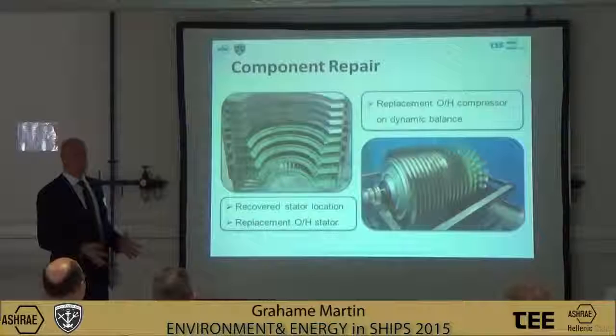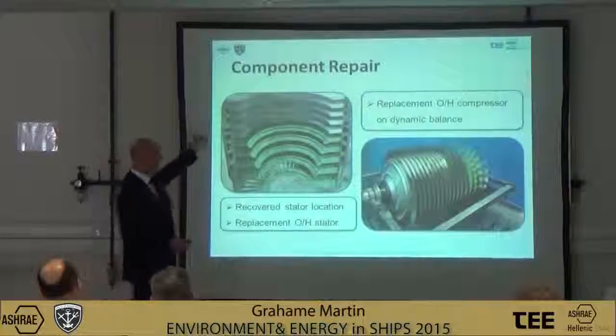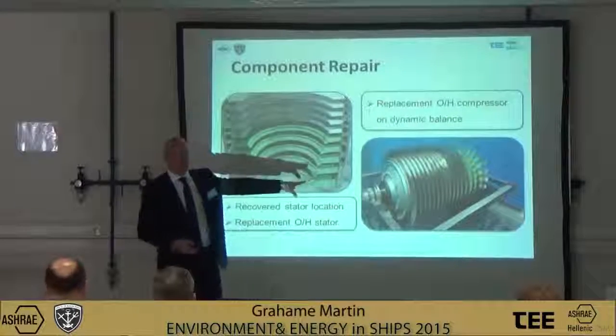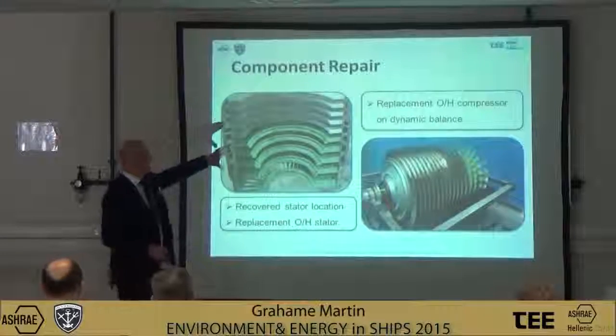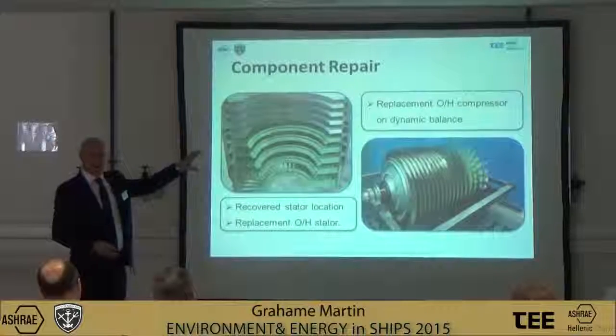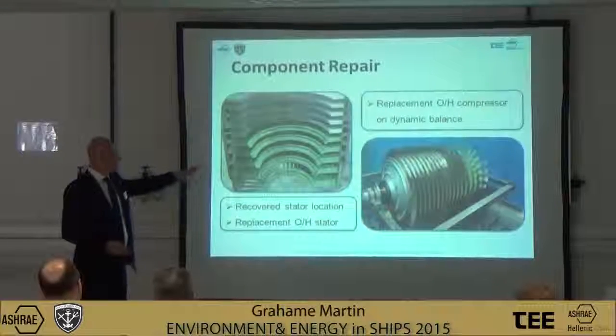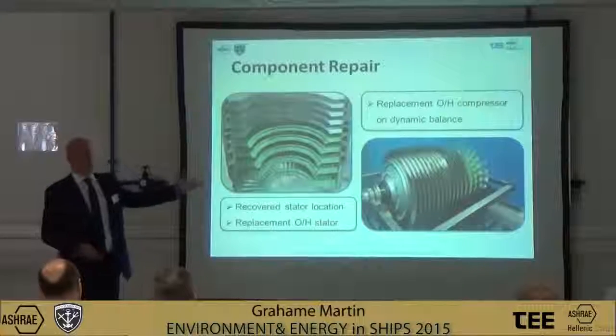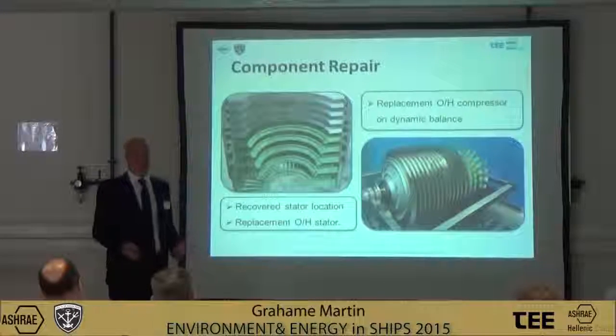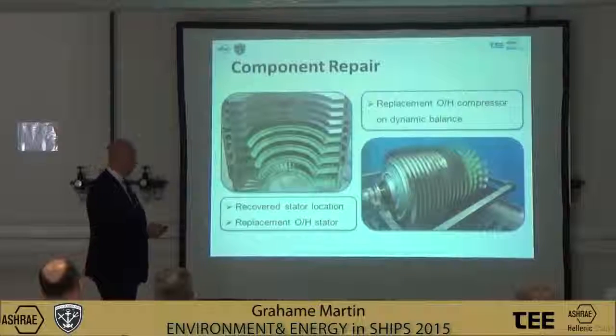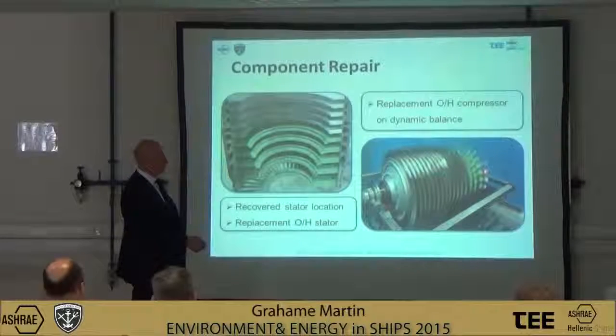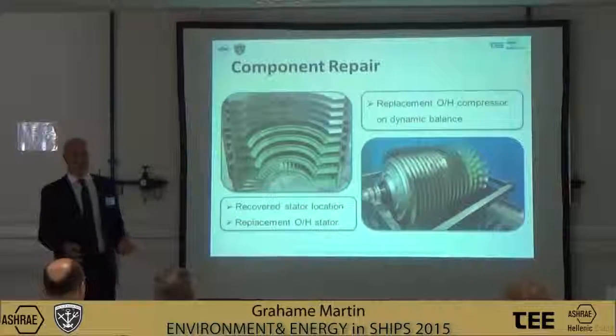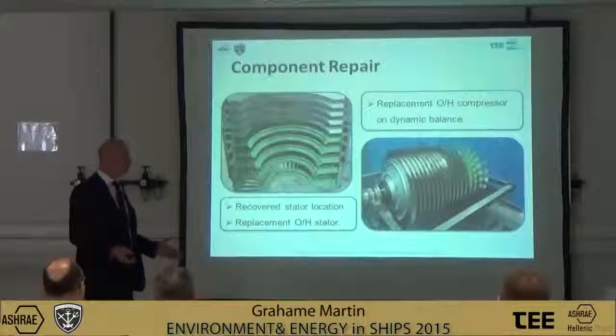So this is what we did. This is exactly the same compressor casing, the same compressor rotor. We were able to recover the casing land where the compressor stator is located. We obviously had to replace the stator itself because it was beyond repair, and also the blades within the compressor itself were replaced. There was no recovery for that amount of damage.